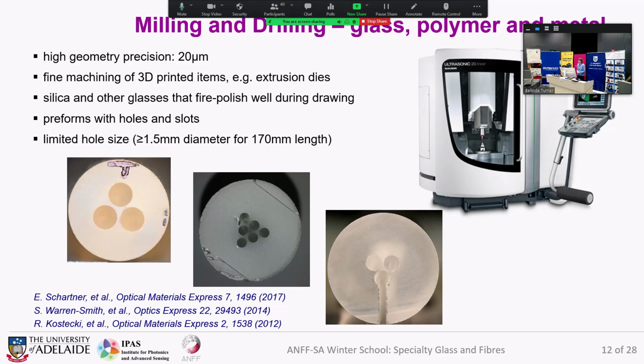And so therefore, we also have a high precision 5-axis CNC. Often we first make a part via 3D printing, and then it goes to our CNC, and then we fine machine it to achieve the geometrical precision of 20 micrometer. Our CNC can be used for metals, glass, and polymer because we have an ultrasonic function. We use it also for creating holes and slots into glasses, and this is another way of creating preforms with air holes.